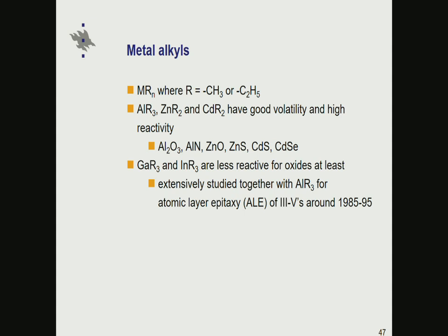It would be quite tempting to just go down in the same group in the periodic table from aluminum to gallium and indium, but I would say that in general these have been quite disappointing, in the sense that the high reactivity which aluminum molecules exhibit is much less for gallium and indium. These were studied quite extensively in the late 80s, early 90s, when there was a lot of effort towards exploiting atomic layer epitaxy, as it was called in those days, for making 3-5 compounds like gallium arsenide and so on.